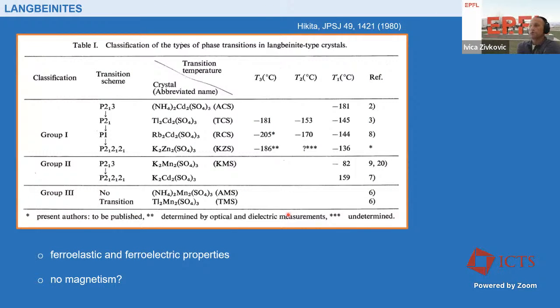If you do a little bit of research on what has been done on langbeinites before, you will actually find very little. Actually, these guys were investigated in the late 70s and through the 80s in the context of renormalization group. So in the 70s, when the renormalization group theory had been developed, there was a lot of investigation of magnetic properties in soft ferromagnets, searching for universal classes, critical exponents, and so on. And it seems that langbeinites have been investigated in the same context, but now from ferroelastic and ferroelectric properties.